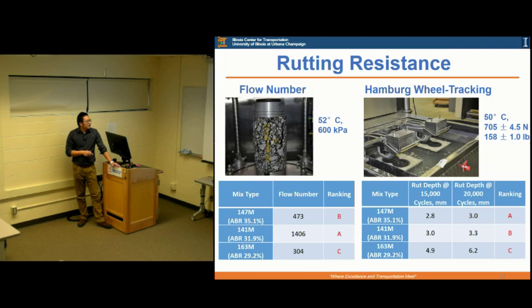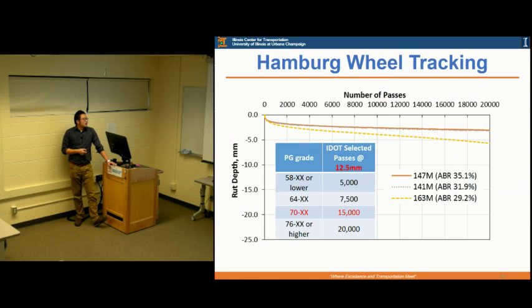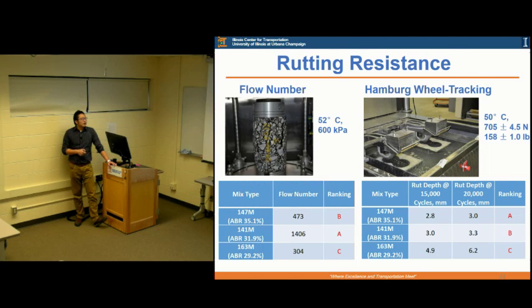If you look at the results for the three mixes, they give you different rankings. For example, if you look at flow number, this gives 141M the best rutting resistance. But if you look at the Hamburg wheel tracking, you get different ranking results, because these two methods have different conditions—one confined, one unconfined. Also, the flow number had a very high variation. Even though I didn't show it here, it has a much larger variation than the Hamburg wheel tracking test.